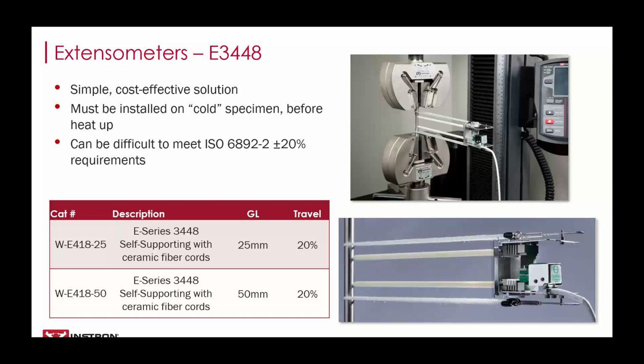So taking a closer look at a self-supported extensometer, this is one of the most popular models that we see. It's simple and cost-effective, and the 50 millimeter or 2-inch gauge length version is really well suited for strain control testing to ASTM E21. For smaller gauge lengths, it can be more difficult, as we discussed earlier, and trying to meet 6892-2 with this extensometer is not recommended. In those applications, you'll want to upgrade to one of the hot mountable units. But again, if you're testing 50 millimeters or 2-inch gauge lengths to ASTM E21, or if you plan to strictly use crosshead control, this is a perfectly suitable option.